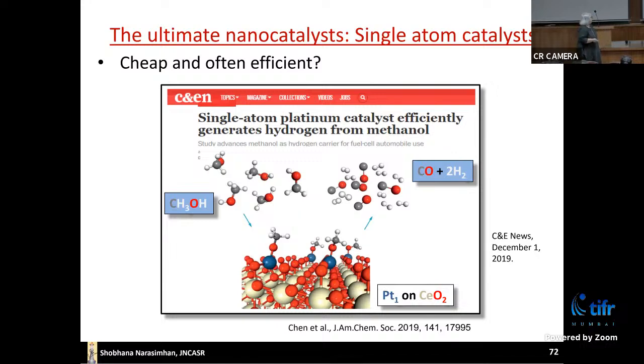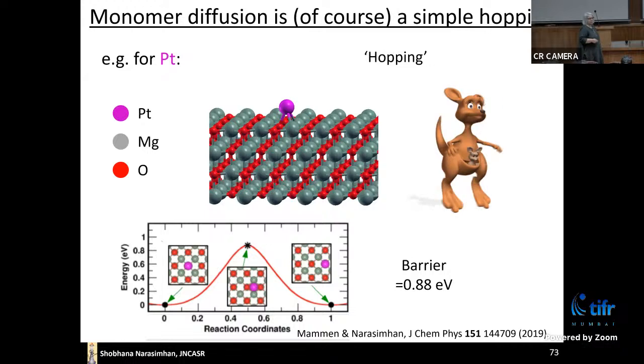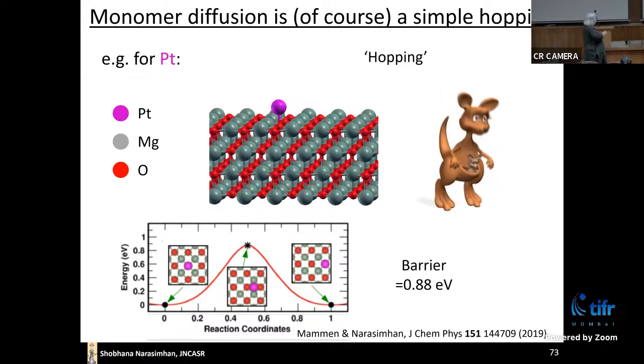Okay, so the first thing we did was we put a single platinum atom on an MgO surface and we checked how it moved. And you see it moves as one would expect by process of hopping.